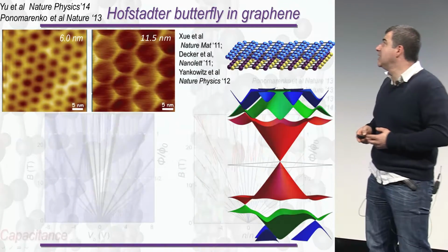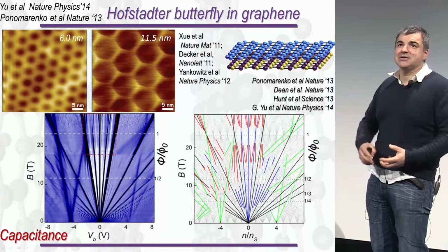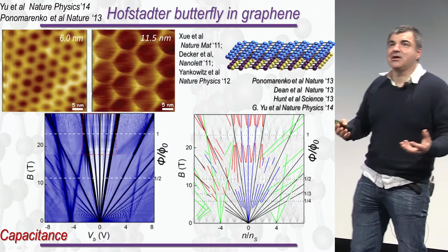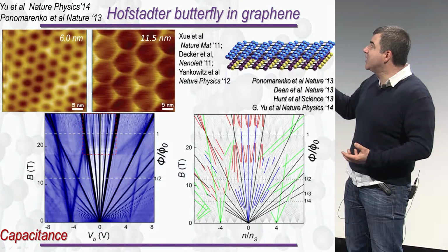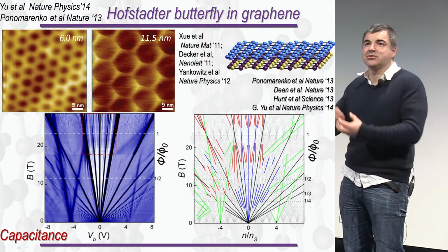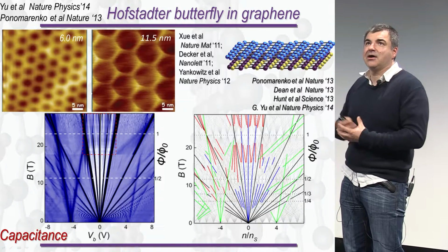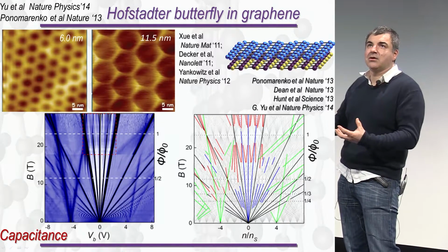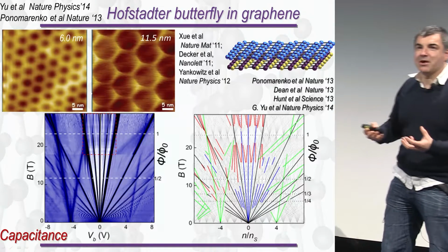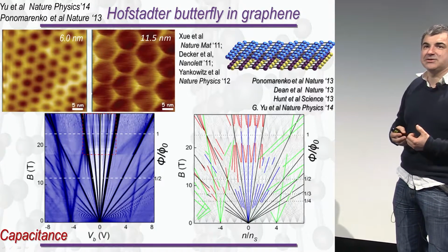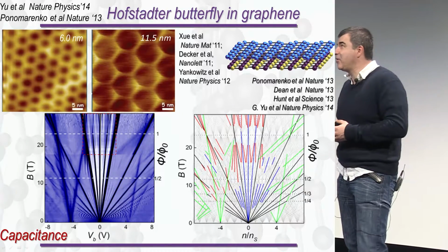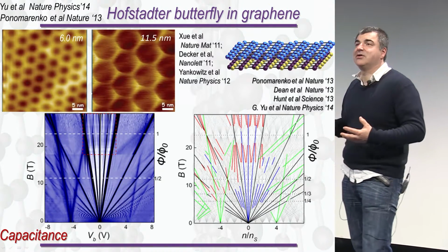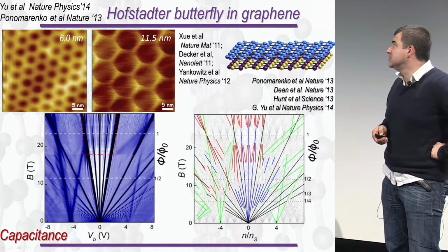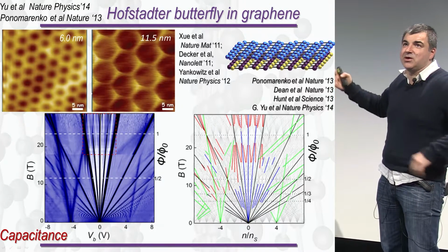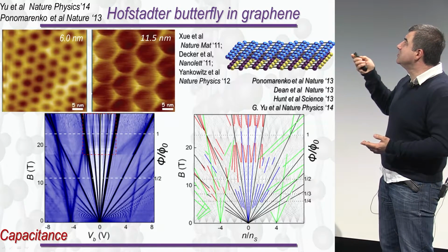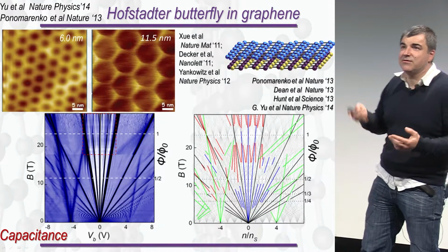But what is interesting is that if I apply magnetic fields, I get even more interesting particles, which consist of electrons scattering in this potential, but they also acquire one flux quantum of magnetic field. So they are quite complex quasi-particles, but their properties are extremely exciting, and it's good fun to study those. And it's simply because we can interact two layered materials, graphene and boron nitride.